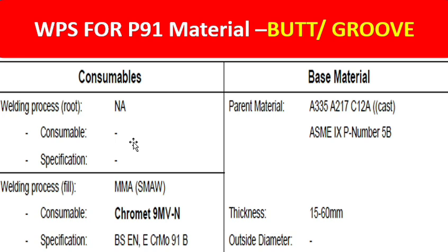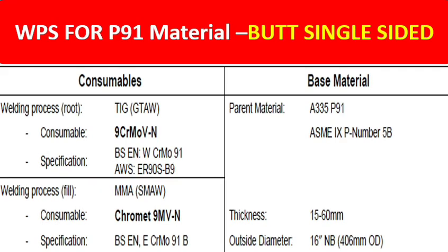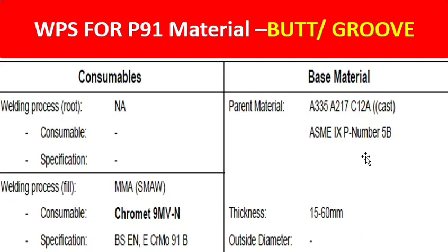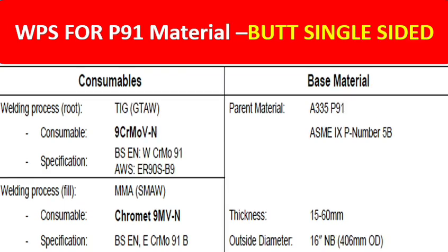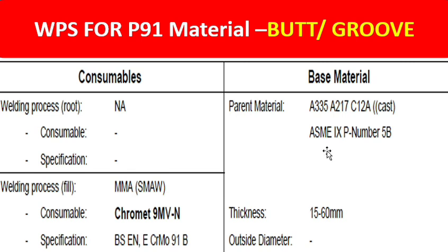You can see here the parent metal in the first one is A335 P91. The other is A217 C12A, so this is cast. After the cast, the material comes from A335 P91. This is also the same P number, 5B. Thickness is 15 to 60 mm. Outside diameter is not applicable.